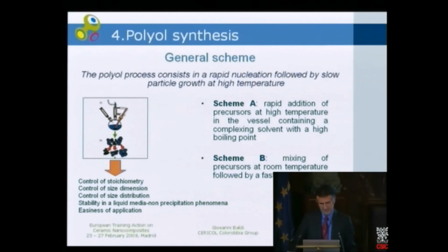This is a very interesting synthesis. The polyol process consists of a rapid nucleation followed by slow particle growth at high temperature. Generally, we use a complexing solvent with a high boiling point in which this nucleation step occurs.